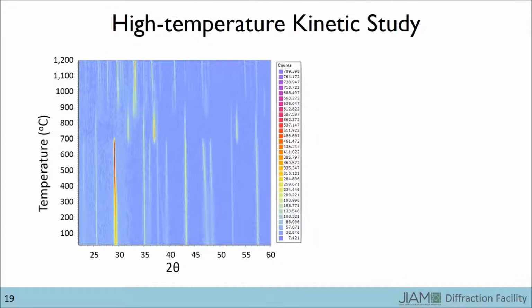The next high-temperature example has a plot that looks vastly different than the last one. For this kinetic experiment, the data were collected while the temperature was increased to 1200 degrees Celsius. Never did the user allow the system to pause at a temperature to reach equilibrium. Each of the vertical lines that you see in this plot corresponds to a peak in the typical intensity versus 2 theta type of plot. The color of each line indicates the intensity of the peak.